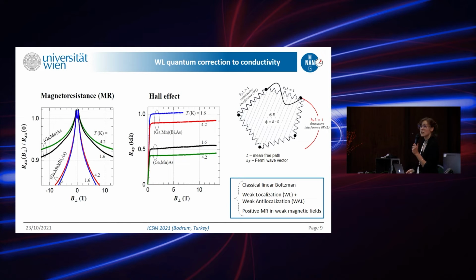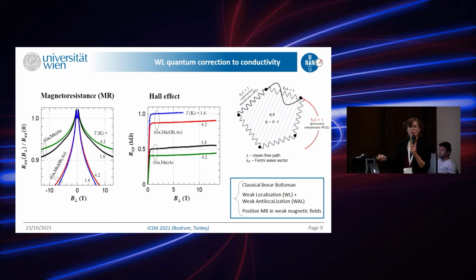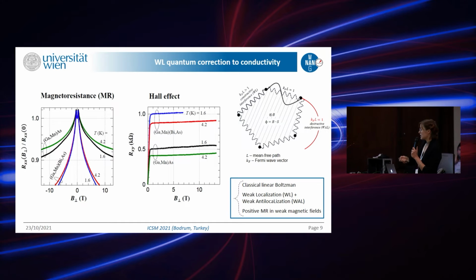And in order to do that, we decided to apply the weak localization quantum correction to conductivity. To perform that, we applied our high magnetic field perpendicular in this case. You see another interesting combination of Hall effect presence. In lower fields, when the field is applied perpendicular, we see the anomalous Hall effect, or the contribution of magnetization. But when we reach high enough fields, there is a classical behavior from which we can characterize our carriers, the holes, and their concentration, which was 2 times 10 to the power 20.